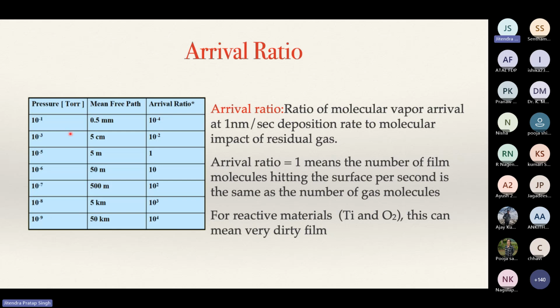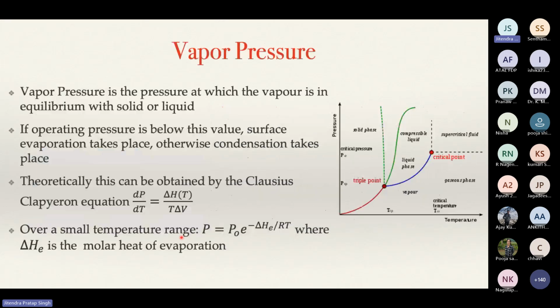You can obtain this only at very high vacuum. That's why in the clean room we always deposit under ultra high vacuum. If I have ultra high vacuum, it ensures that my arrival ratio is like 10,000. So for one gas atom, we have 10,000 atoms of our depositing material, which ensures that we really get a contaminant free film. That is very important.